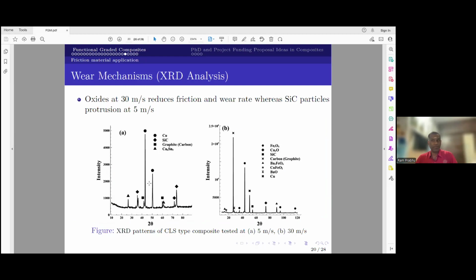Then to look at what kind of oxides are formed. At low sliding speed we didn't see any kind of oxide formation, which is another proof that abrasive wear is dominant. You can see here, only the elements we have used to build the composites exist, and some kind of reaction happened between copper and tin. But when you go to the higher sliding speed, we can see a number of oxides: iron, copper, barium iron oxides, copper iron combination oxides, and so on. You also have a tribo layer, so that's why you have graphite as it is. So this again corroborates the observation of oxidation wear existing at the higher sliding speed and absent at lower sliding speed.